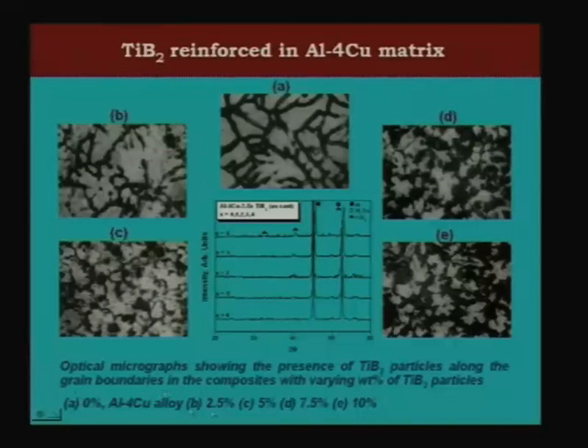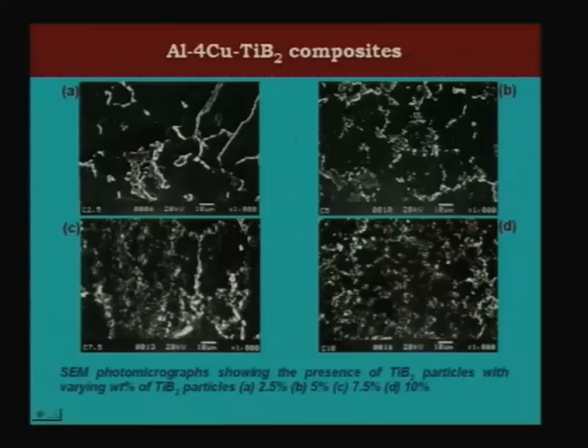So if you take this kind of aluminum copper alloy and add different amounts of, not precipitates, reinforcement: 2.5%, 5%, 7.5 and 10%. As you can see here, different volume fractions have been added to an aluminum copper base alloy, and then look at all this. You can see with increasing percentage of TiB2, the peaks of TiB2 become bigger and bigger, and these are the SEM photographs showing higher volume fraction of these TiB2 particles.